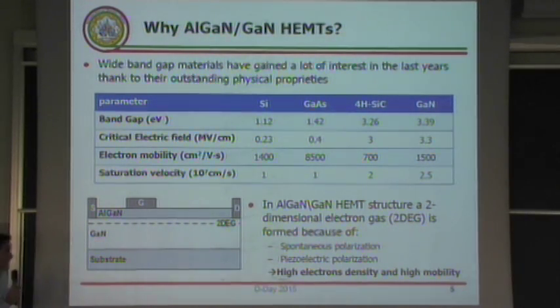Gallium nitride is a wide bandgap semiconductor because it has an extremely high bandgap when compared with the traditional semiconductors used in electronics, as you can see in the first row of this slide. This helps the material achieve extremely high critical electric fields. This is a good point for high voltage applications, because using this material it is quite easy to obtain high breakdown voltages. Moreover, gallium nitride also has very good electron transport properties, like high saturation velocity and high electron mobility.